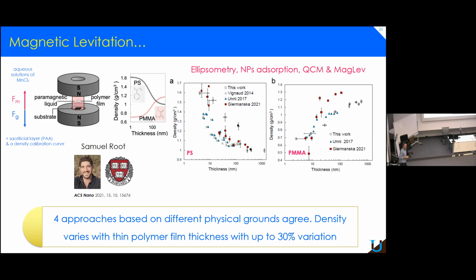Do they allow in the experiment the film to equilibrate to the extent that it forgets where it came from? Because we're showing that there's a strong impact of the layer close to the interface, close to the substrate, and it takes a very long time to forget about this initial adsorption. So perhaps it has residues. Yeah, that's a good point.